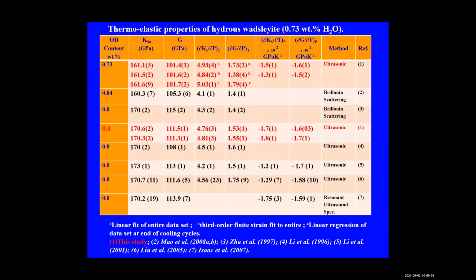We also measured the anhydrous phase, the one with 0% water. We did that in order to validate this technique, because most of the time when we measure the elasticity of the anhydrous phase, we usually measure it at very high temperature. So we wanted to repeat the same experiment here to validate the results. You can see that the K and G from our data for the anhydrous phase are in good agreement with the results from Brillouin scattering and other ultrasonic studies from previous work in the table. But although the pressure dependence of our K for the anhydrous Wadsleyite is internally consistent, we can see that it is high compared to the Brillouin scattering data.